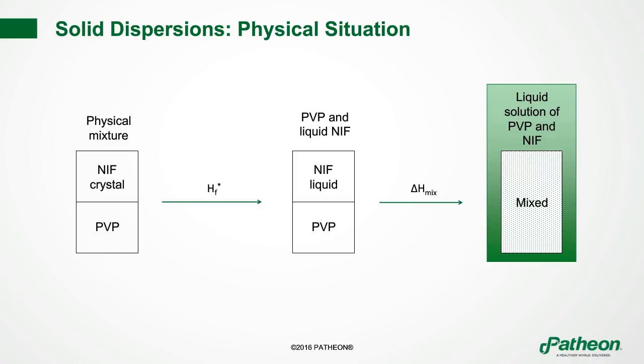Then what you do is you add heat to the system. And what you see is the heat of fusion, and that's for the drug molecule. So as you add heat to the system, the drug molecule, which is a crystal, is going to actually melt. And it takes the heat of fusion to do that. So you have to add a certain amount of heat into the system in order to get the nifedipine crystal to melt. Before you get to the melting point, you're obviously going to raise the temperature of the entire system, so that's additional heat that you're adding. But once you get to that heat of fusion point, the melting point of the crystal, you have to add in the heat of fusion in order to melt the crystal entirely.